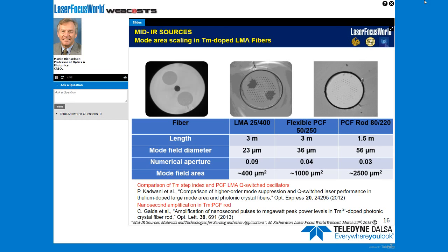And of course, for pumping these with high power diodes, we need to have the highest possible numerical aperture for being able to effectively pump these types of fibers. In fact, although we associate most fibers with being flexible for optical fibers, particularly from communications, there is now a class of fiber lasers which uses, in essence, solid photonic crystal fibers, literally rods of photonic crystal fibers that have fairly large dimensions, as you can see on the right-hand side. There are some references I've given you at the bottom there for where you can follow up, but of course there are many references to the development occurring with high power fiber lasers, but they are of course still limited down to the extreme short wavelength end of the mid-IR region.